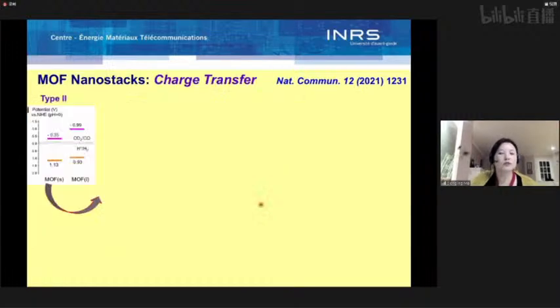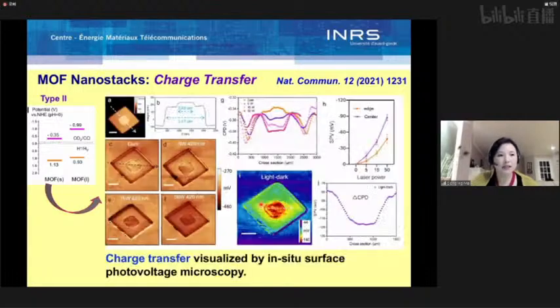So based on all these characterizations, we can see the bottom and the top nanoplates differ slightly. Because of that, they also show quite different band gap structures and different energy levels. This is basically obtained from our experimental data and also confirmed by theoretical calculations. So we think with this type 2 structure, we should get extended absorption and also efficient charge separation between